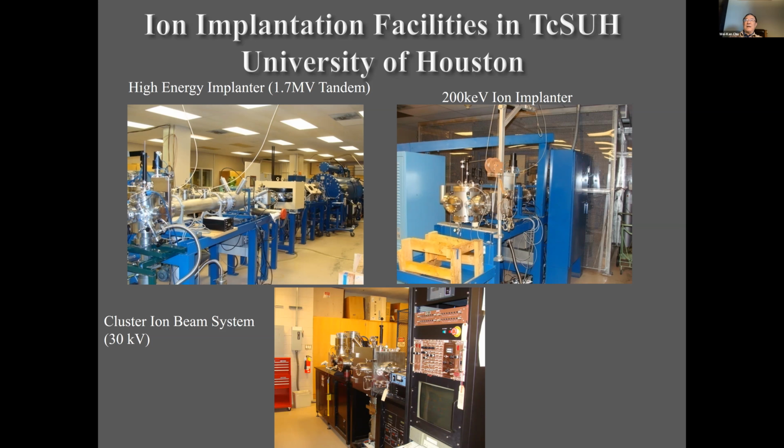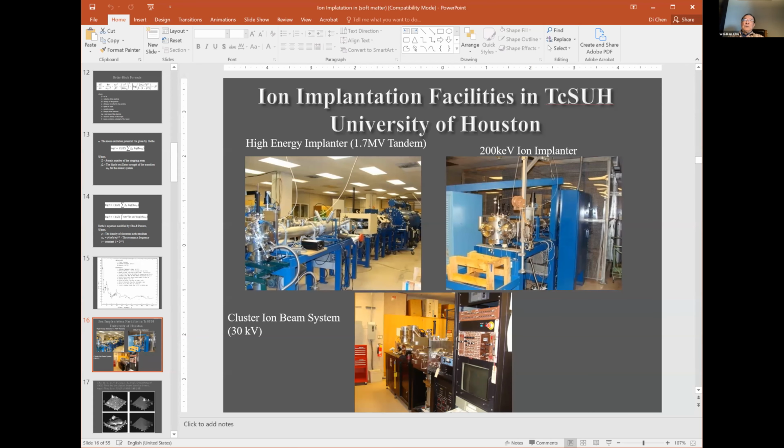So this is almost like a spherical droplet with 3,000 atoms moving together, and they only have one electron missing. That means it's singly charged, with 10 electron volts equivalent per atom. So this is very, very slow, very gentle. It just goes down the vacuum until it reaches the target. Next graph.